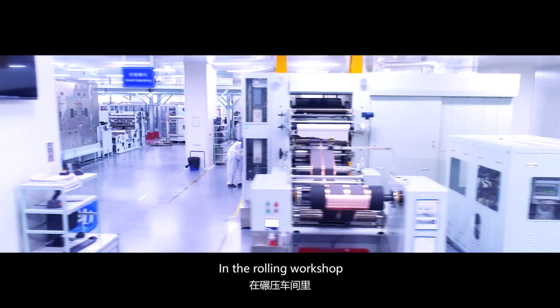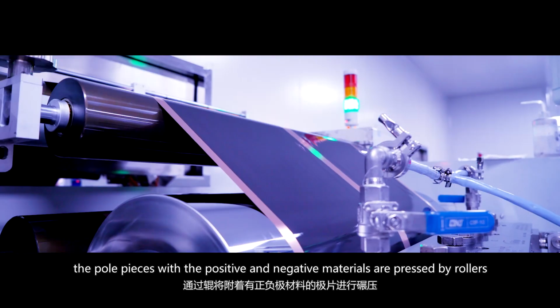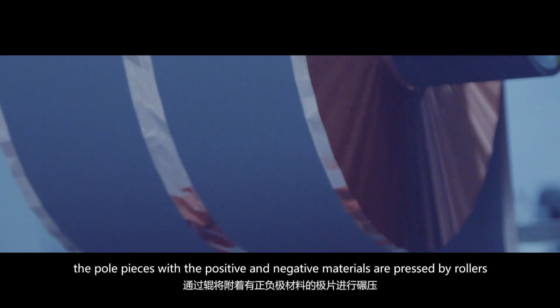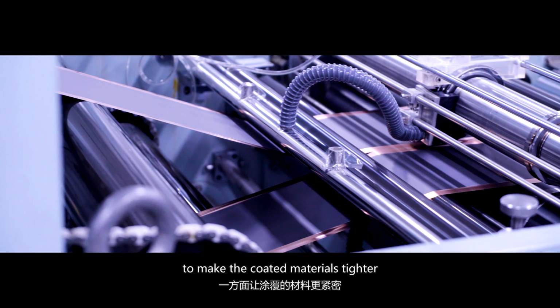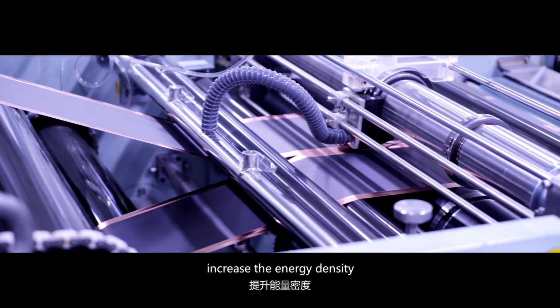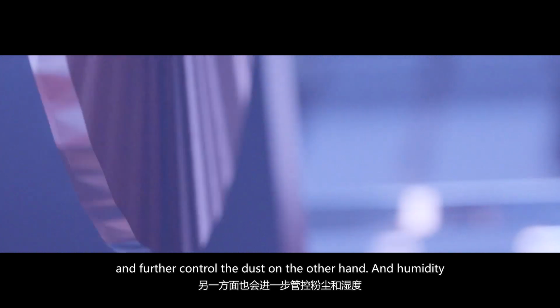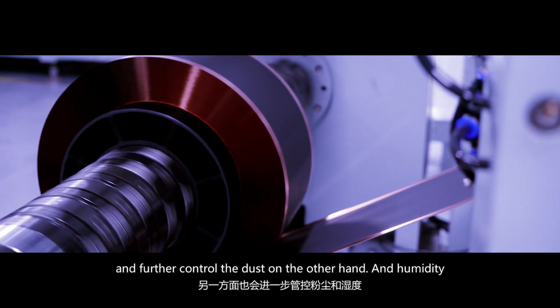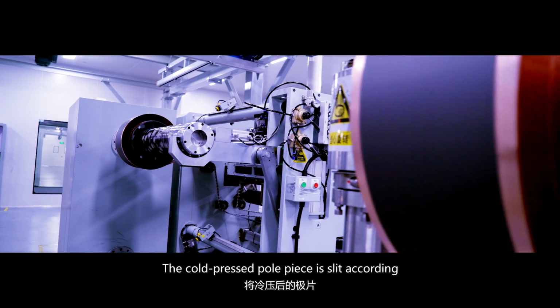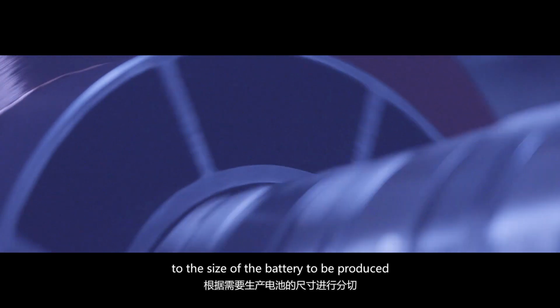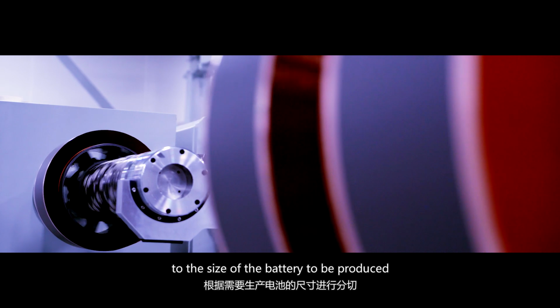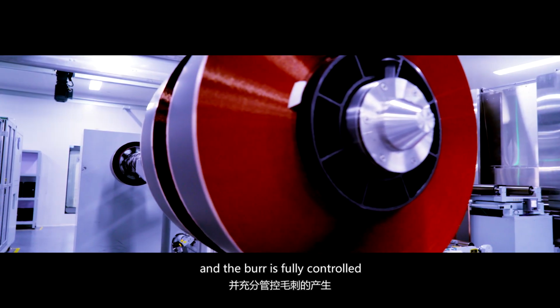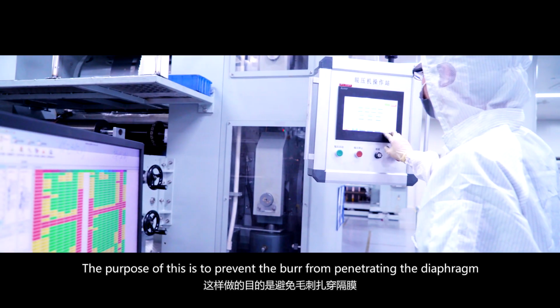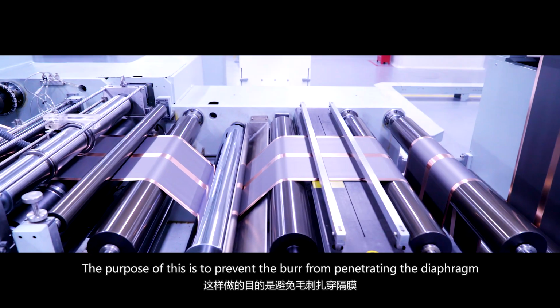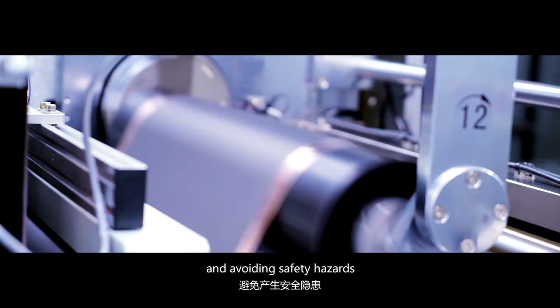In the rolling workshop, the pole pieces with the positive and negative materials are pressed by rollers to make the coated materials tighter, increase the energy density, ensure the consistency of thickness, and further control the dust and humidity. The cold-pressed pole piece is slit according to the size of the battery to be produced, and the burr is fully controlled. The purpose of this is to prevent the burr from penetrating the diaphragm and avoiding safety hazards.